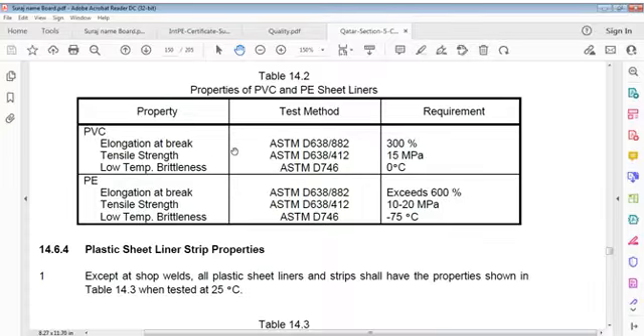So elongation at break is according to ASTM D638, 300%. Tensile strength is according to ASTM D638, 15 MPa. Low temperature brittleness is ASTM D746, 0 degrees Celsius.